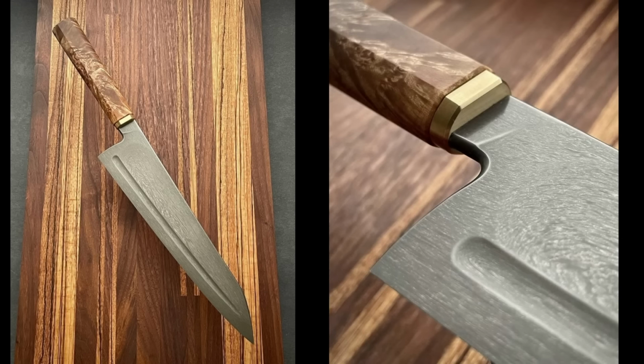I'm not sure. Some knife makers will also etch their commercial steel knives because they have carbide banding in them just due to the alloy segregation and carbides and everything that the steel company cannot get rid of. When you have a high alloy content, those carbides won't dissolve at the melting temperature. They can't get rid of them. And so carbide banding is basically just a natural result of making the steel. And most of these knife makers don't call it Wootz, but this feature is seen as desirable to some knife makers and some buyers. So like, for example, this is a knife by Dan Bidinger. I don't actually know how to pronounce his name. And it's made in A2. He gives it a light etch, and it has a very cool macroscopic banded structure that looks very similar to Wootz. Could you call this Wootz?